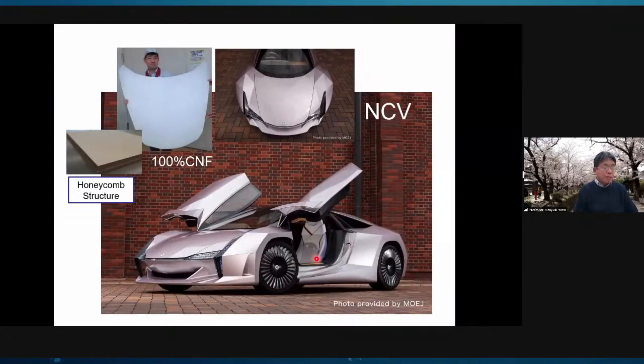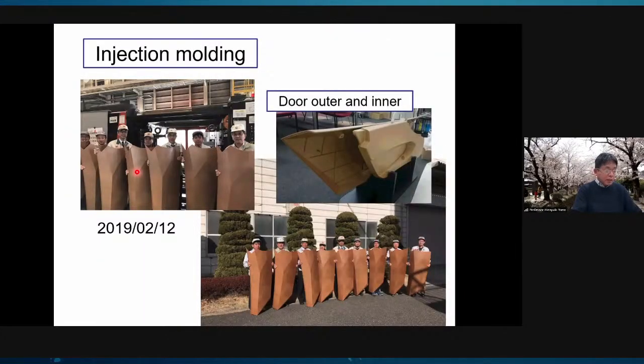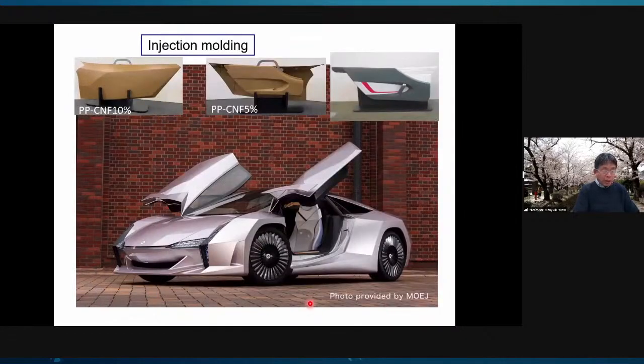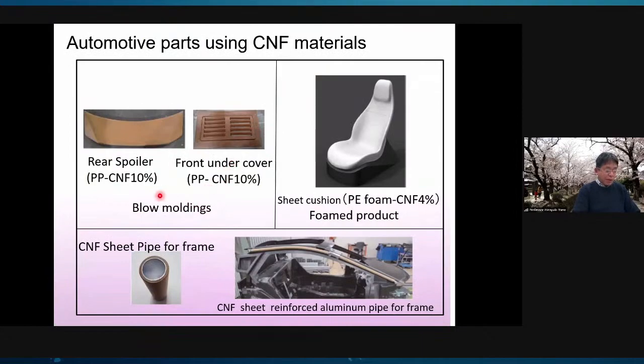Okay. NCV has a bonnet made of 100% CNF honeycomb board. And these are injection molded outer parts of the door. Outer parts of the gull wing door are made of injection molded foam, 10 weight % cellulose nanofiber reinforced PP. And the inside door trim is injection molded foam, 5 weight % CNF PP. We made a rear spoiler and front undercovers by blow molding.